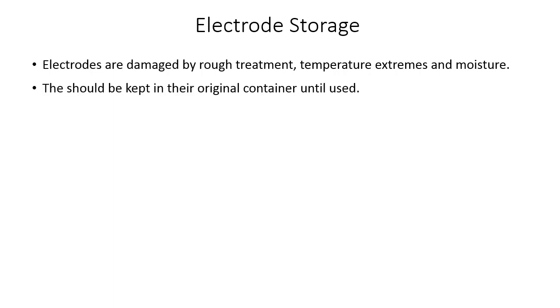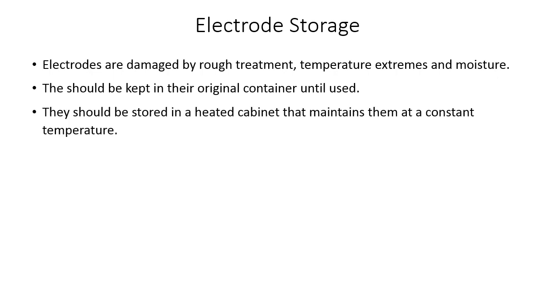They're designed to reduce underbead cracking in alloy and medium carbon steels by reducing the amount of hydrogen in the weld pool. The flux is hygroscopic, which means it attracts moisture, and with low hydrogen, we don't want moisture. The moisture in the flux also causes excessive gases to develop in the weld pool and causes porosity. So this is why it's very critical to take good care of your electrodes.